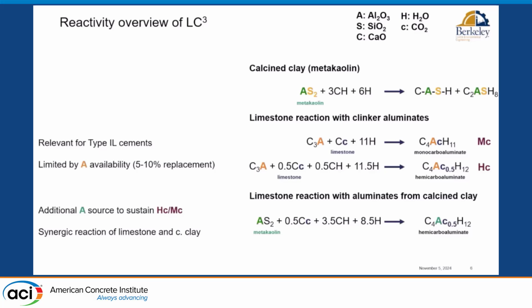The interesting thing is when you have an additional source of alumina, in this case the calcined clay, because here the alumina from the calcined clay can actually react further with the calcium carbonate to form more hemi and monocarboaluminate. And this is why we hear these phases mentioned surrounding LC3, because we actually form more of them in this system, because we have so much alumina available by providing calcined clay. But this would be also the case if you use fly ash or other SCMs that contain alumina. It's just that the process is going to be slower because you're limited by the dissolution rate of your SCM.